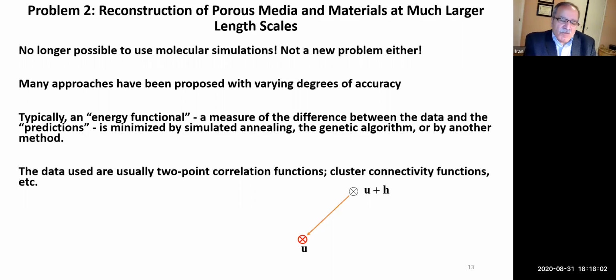Normally, these approaches that have been introduced have an energy function. The energy is basically the difference between the data that you have and the predictions that your reconstructed model provides, and you want to minimize it. In order to minimize that difference, people use various optimization methods such as simulated annealing or genetic algorithm or another method. But normally they use 2-point functions. In other words, they look at one point, let's say at U, as you see, and then they collect statistics at another point at a distance h from that point. So these are 2-point statistics, which are good, but they do not give you information on long-range connectivity of the structure, which is the most important.